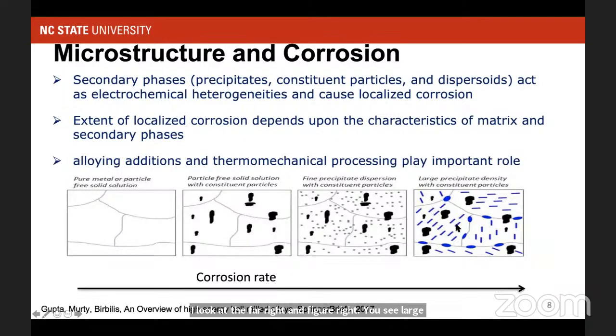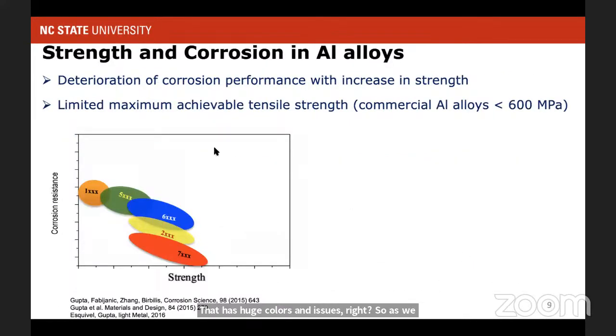We call them precipitates. They could be a few nanometers in length scale, and they are closely spaced, and they provide all the strength. So they are needed. But from a corrosion perspective, their electrochemical properties are very different from the matrix, and they interact with the matrix and cause localized corrosion, and the corrosion becomes a huge issue. So now I take pure aluminum, highly corrosion resistant. I go to 7075 T651 that we use in aircraft. That has huge corrosion issues, right?